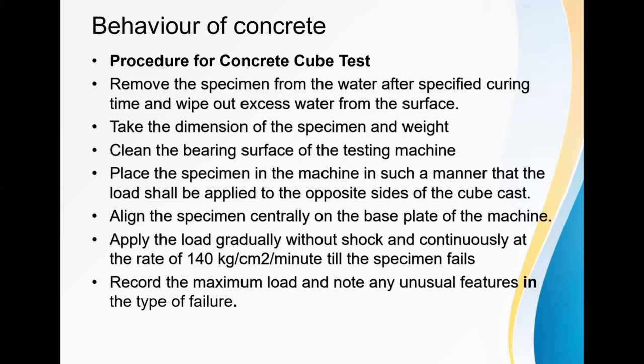Then gradually apply the load without any shock, that means sudden load, and continuously at a rate of about 140 kg per centimeter square per minute till the specimen fails. Record the maximum load and note any unusual features in the type of failure. This gives the compressive strength of the particular grade of concrete of the structure. Generally, we consider the 28 days compressive strength of the concrete for achieving the required minimum strength and durability.